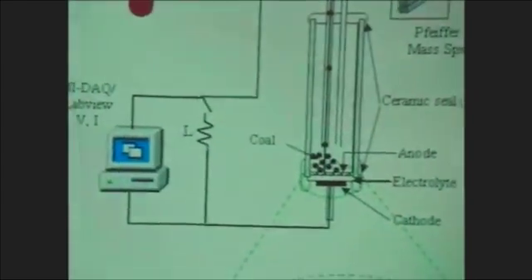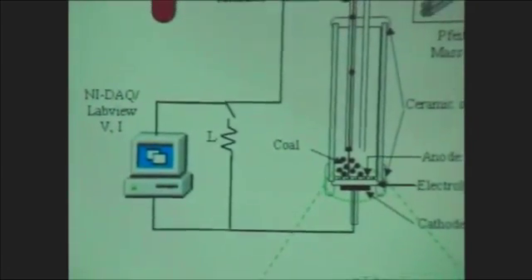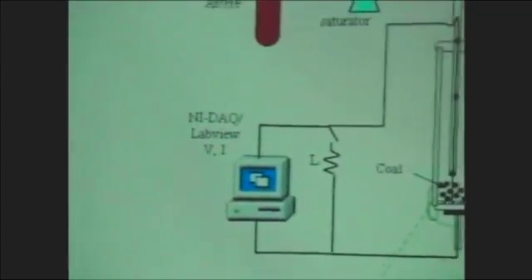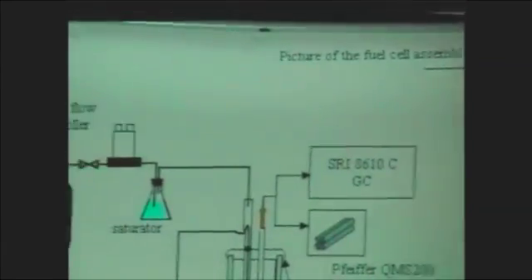One reason why we got into carbon is simply that we are not experts in solid oxide fuel cells. We have trouble getting all these fuel cells sealed well, and there's always an explosion hazard in the lab. Because if we send the hydrogen in, or the methane in, and heat it up at high temperature, there's a chance the whole system can catch fire and cause an explosion. In our lab, we have a lot of activated carbon, so we decided to use carbon as a fuel to do the electrochemical oxidation.